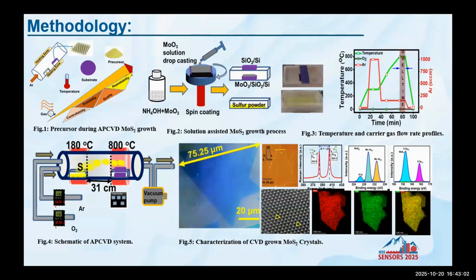So this is the synthesis process for the monolayer MoS2. Here I have used a solution-assisted process for monolayer growth of the MoS2. MoO3 powder is dissolved in ammonium hydroxide solution, and this solution is spin coated on a SiO2/Si substrate. This MoO3 coated substrate is kept at the bottom of the alumina boat, with another SiO2/Si substrate kept on top of it to trap the sulfur flux between these two substrates. In another alumina boat, we take the sulfur powder.